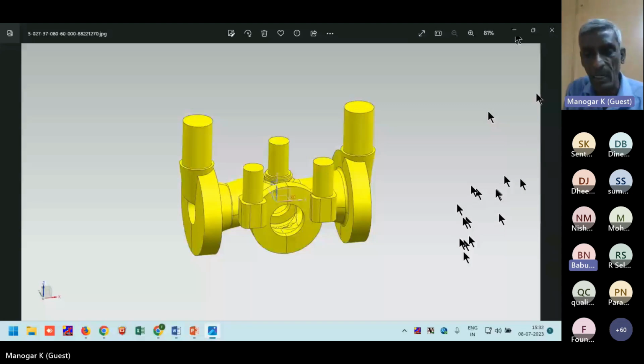Okay. Generally, in insulating, depending upon your casting, you are deciding the size of the riser. So now we have discussed how to calculate the riser size. Actually, the sleeve suppliers are supplying sleeves of more than 6 inch only in insulating sleeves. They are not exothermic. The exothermic risers have more efficiency. It is explained in the table, that is 40 to 50%. The insulating sleeves have lesser efficiency, that is feed metal. So you may need a bigger riser when you are using an insulating riser. If you use the exothermic riser, then you will get a better yield. Sir, generally in insulating sleeves, we are getting 1.4 to 1.5 modulus extension factor. Okay. And in exothermic, generally, as per the supplier specification, it is coming 1.6 to 1.7. Okay. But practically, I will check. You have to confirm from your side.